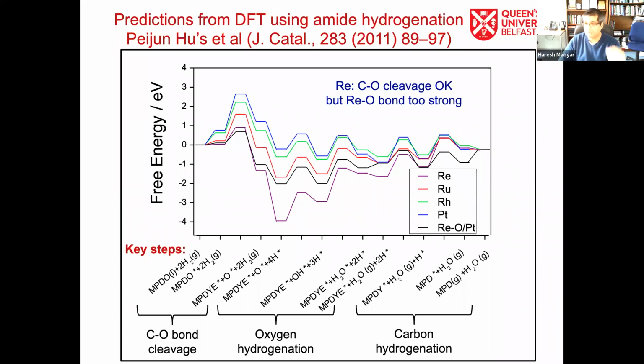conditions, low temperatures, low pressures, enhance the catalytic activities, use better catalytic materials and use better reaction technologies, better reactors to achieve more efficiency and increase the yield of the product. So in this case, again, with Professor Pejin, with his DFT calculations, we predicted what should be the pathway on the metal oxide materials that will use the lowest activation energy barriers. So we came up with a mixture of the two metal oxides, platinum and rhenium, and we tried many